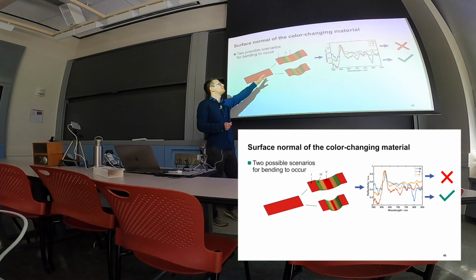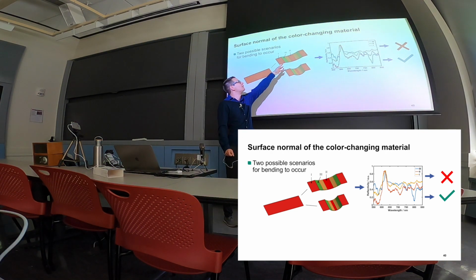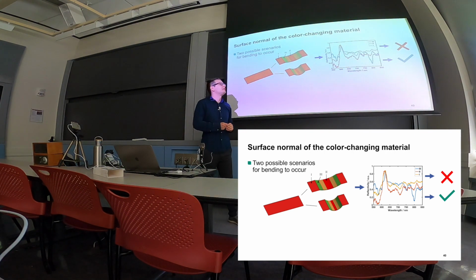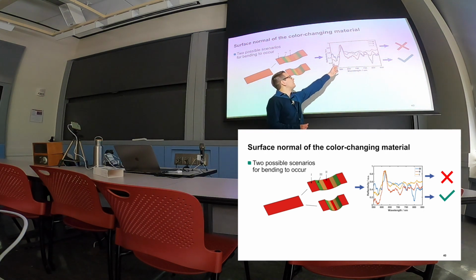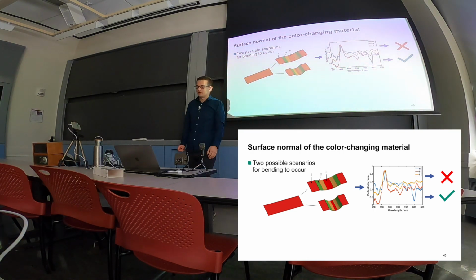And I also measured at the 3 positions that we see over here, 1, 2, and 3, so outside of the cell, inside of the cell, and the edge of the cell, what the peak wavelength is under a perpendicular angle, and I could see that the peak wavelength is the same for all of them, so there's no stretching occurring, and the color change only occurs by a soak-in process of that overall system.